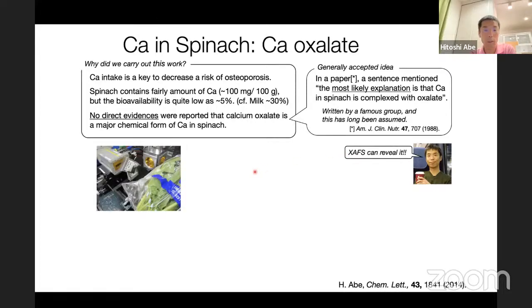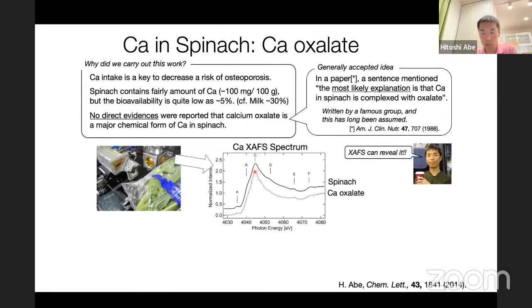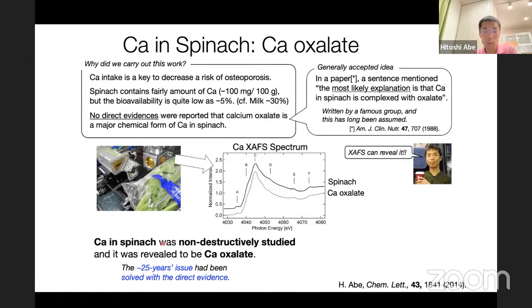And then I performed experiments to confirm whether this is true or not. And this spectrum was obtained. This is spinach, the calcium spectrum of spinach, and the dotted line is calcium oxalate. You see, these are the same. So we can conclude that calcium in spinach is calcium oxalate. This was performed non-destructively. So we say that the more than 25 years issue has been solved with direct evidence.